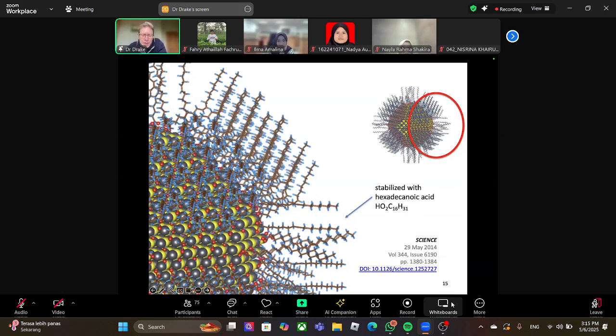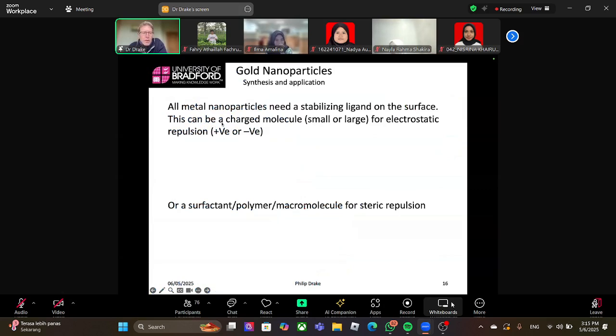And it's the chemistry of this ligand surface, of this stabilizing layer, which determines the chemistry of the particle. The gold has got nothing to do with the surface. You need to modify the stabilizing ligands to modify the chemistry. So all metal nanoparticles, whether it's gold, silver, copper, platinum, need a stabilizing ligand on the surface.